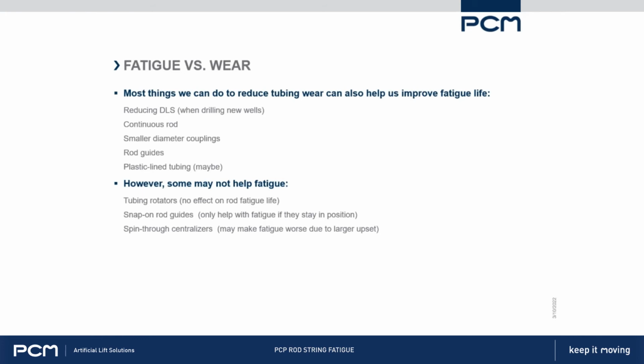I've got plastic line tubing up there. That one kind of depends on the mechanism. Some people have different opinions on how the plastic line tubing actually works. My feeling is that it works by the coupling wearing into that plastic because it's a fairly thick plastic lining. So if it wears into that, even a few millimeters, that allows more of the rod body to be in contact with the tubing, reduces the contact load on the coupling, reduces the wear. But at the same time, it's essentially reducing the upset size. As that coupling wears into the plastic, it's as if the coupling is a smaller diameter in terms of the fatigue life calculations. So it's benefiting you there as well.